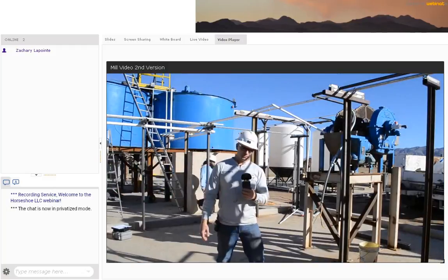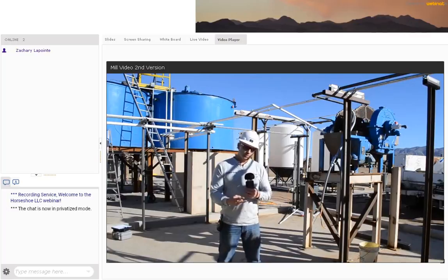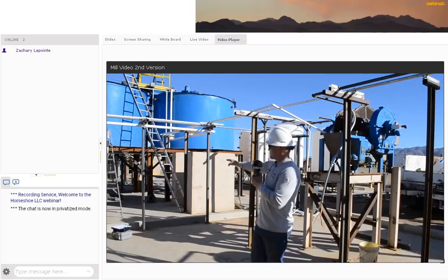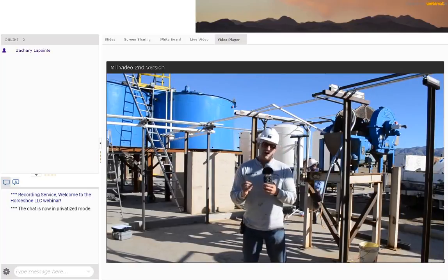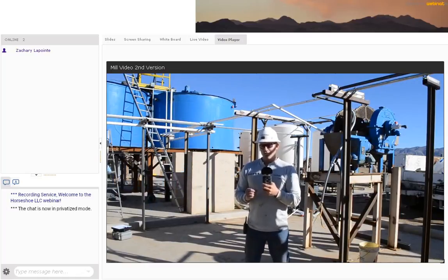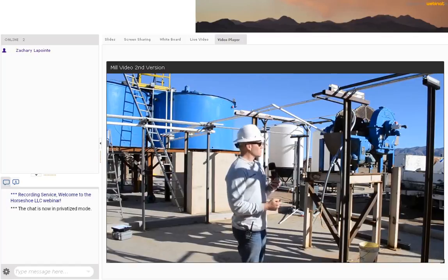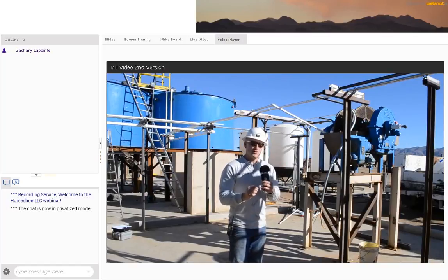Once our solution is passed through the flotation circuits, we are left with 2 materials, one being sulfide concentrate and one being our tails. We plumb both of these solutions into our thickening tanks, the large blue tanks sitting on top of the steel platform. In each one of these tanks we add a small amount of polymer flocculant to increase the settling speed in each. We plumb the processed water to a processed water tank where we recirculate the water through the mill's operations. The sulfide concentrate is plumbed over to a vacuum filter disc pad where we remove any remaining moisture in the product.